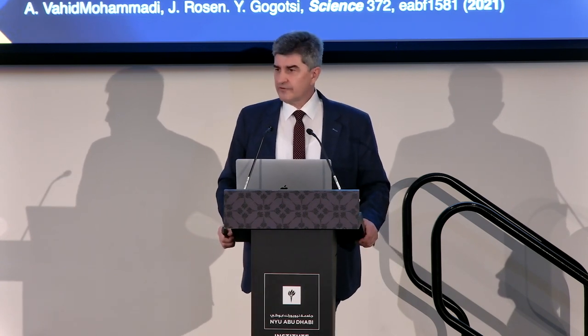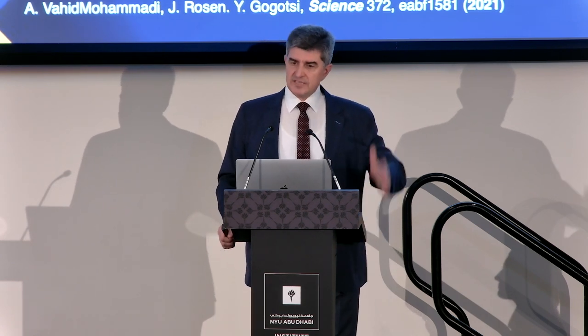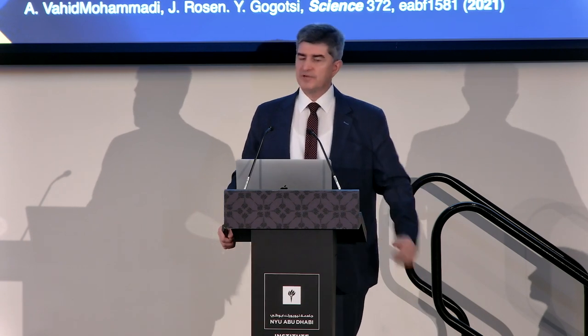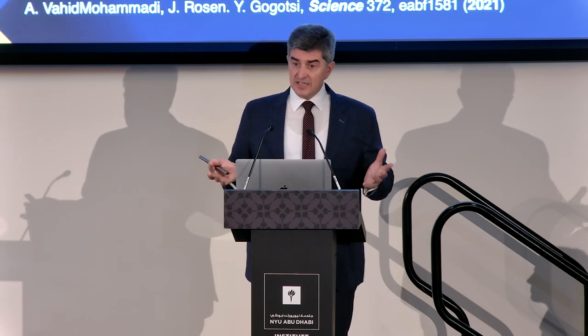Now, surprise. 2 years later, I got a visiting student, a Pakistani guy coming from a Korean laboratory to work with me at Drexel from my Korean collaborator. And we decided to check whether it's really conductivity, because many other MXenes had much lower shielding. We took titanium carbonitride, same structure. We just replaced 50% of carbon atoms with nitrogen. And we knew this material had exactly an order of magnitude lower electronic conductivity. This material appeared to outperform, at the same thickness, even copper, with about 3 orders of magnitude higher conductivity.